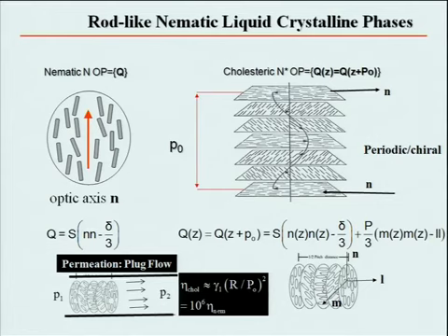So here, if my objects are rods, I have a uniaxial system, unless I put in a field, an electromagnetic field, or an interface or something. But here, at equilibrium without any external fields, we'll see that this system is biaxial, because the plane perpendicular to the helix axis, here denoted by L, is not isotropic. So I look at the plane perpendicular to the optic axis, and the system sees on the left molecules tilting up, and on the right molecules tilting down. So we have intrinsic biaxiality.